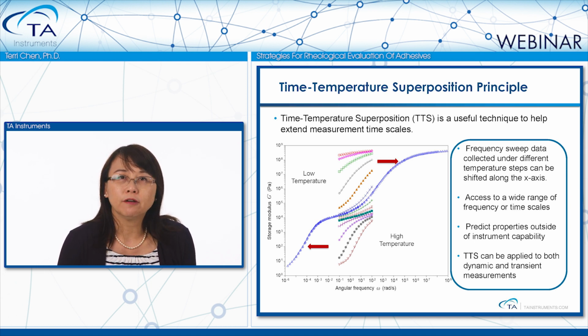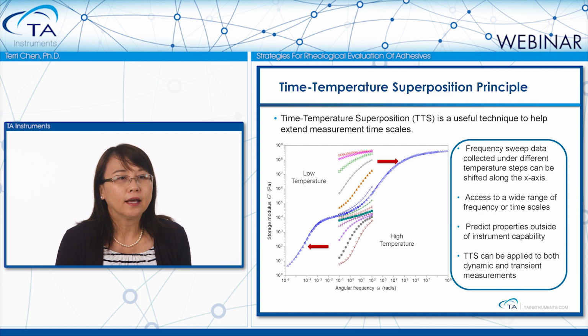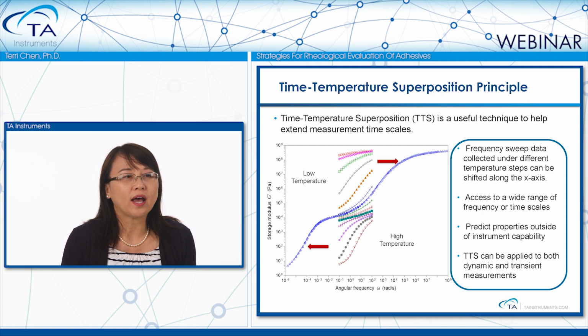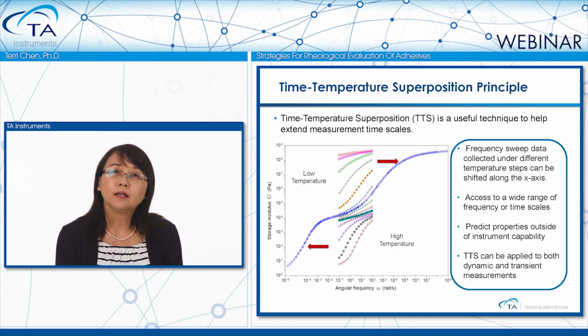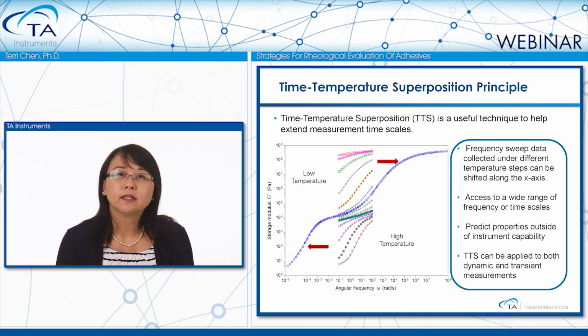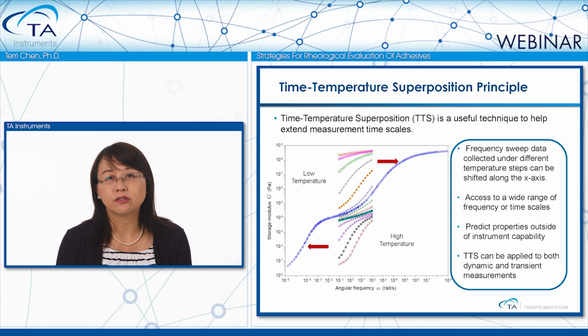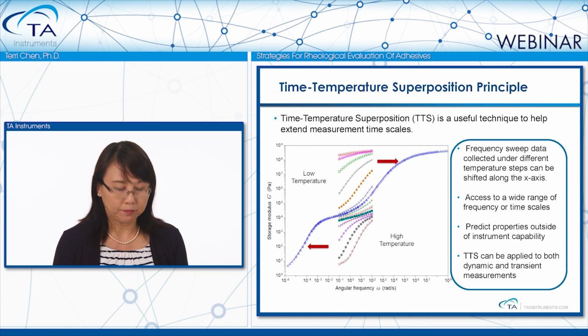After you select a reference temperature, any low temperature data will shift to high frequencies, and the high temperature data will shift to low frequencies. This allows access to a wide range of frequency, which is outside of the instrument capability. In addition to dynamic testing, time-temperature superposition can also be applied to transient tests, such as stress relaxation or creep.